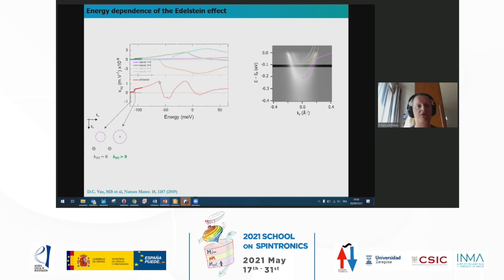Then we increase the Fermi energy and we start to enter the second band, which is shown in green. We have a slightly larger effect. And then we arrive here at this point where we start to populate this orange band, which has a heavy character. And this band has an opposite sign for its Rashba coefficient. And so that's why we see a maximum and then it starts to decrease because you see the orange band has a negative contribution compared to the purple and the green. And we start to see here a little bit already the interaction between the bands and we see the splitting due to the Rashba spin-orbit coupling.